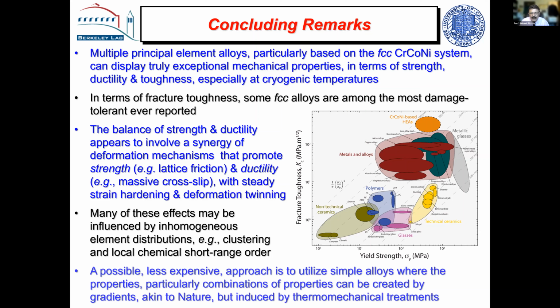But we weren't so concerned about it, because when you go to higher temperatures, which the BCC materials, of course, are geared for, that difference due to local ordering tends to disappear, as you might expect. But yes, you get different effects on screw dislocations versus edge dislocations, so we don't fully understand that yet. There are other problems, I think, with the BCC materials that we're looking at, which is their low toughness and their grain boundary decohesion. But the story is not quite the same as the FCC, you're right. It wouldn't surprise me if you get the opposite effect.